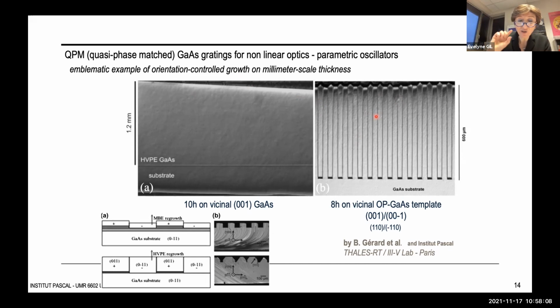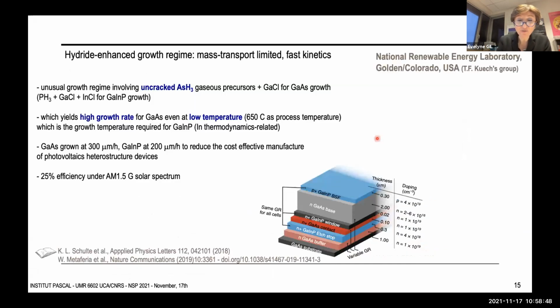And in order to realize the conversion, light must travel through an artificial material matrix composed of alternate 001 and 00-1 oriented III-V semiconductors of sufficient thickness. And the periodic inversion of orientation allows to rematch the phases of the excitation and generated lights in their travel through the matrix to overcome the destructive interferences. So let us continue with the property of fast growth.